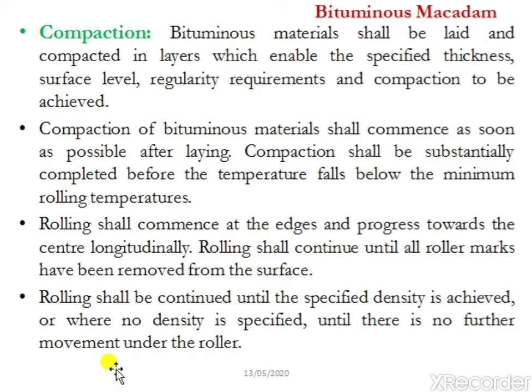Compaction of bituminous materials shall commence as soon as possible after laying. Compaction shall be substantially completed before the temperature falls below the minimum rolling temperature. So once the material is laid over the base, the operation of compaction should be started as soon as possible, and completed before the temperature falls below the minimum rolling temperature. If the temperature falls below it, the mix will become hard and proper compaction is not achieved, and hence the strength of the bituminous mix will not be achieved.